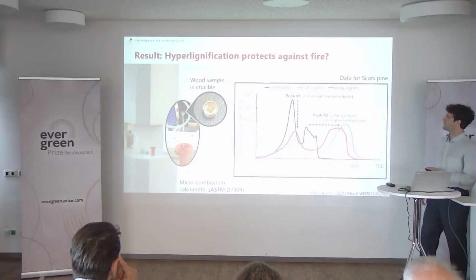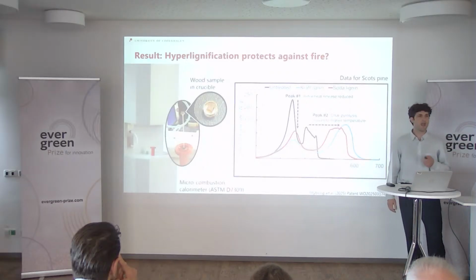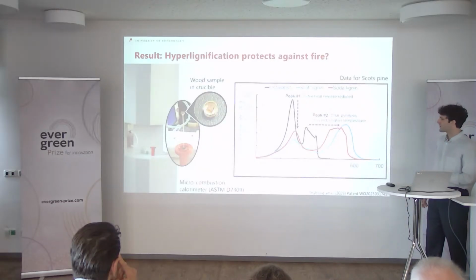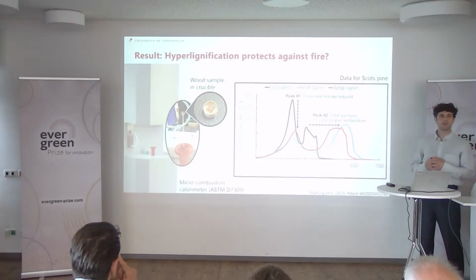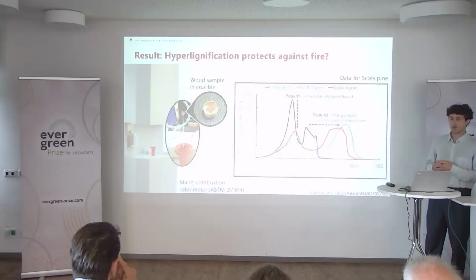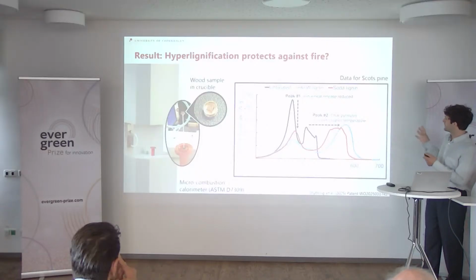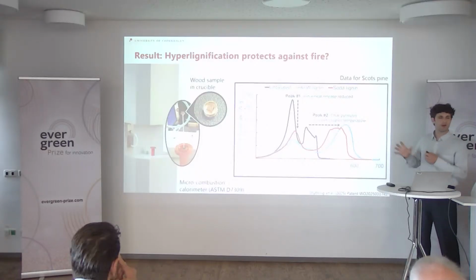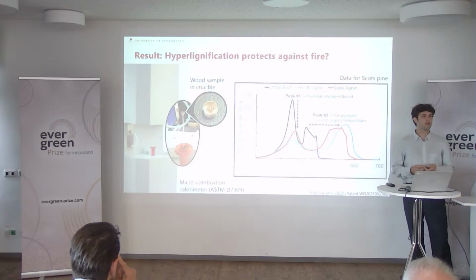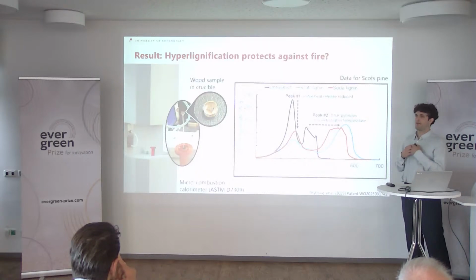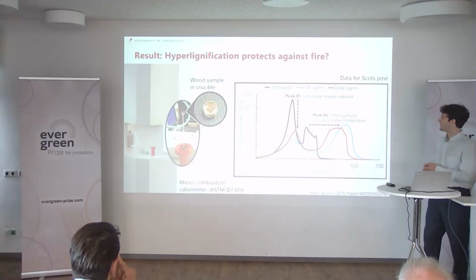And then we wanted to test fire retardancy, and we saw with microcombustion calorimetry that the initial heat release was reduced when we burned hyperlignified wood, while the char pyrolysis peak moved to higher temperatures, meaning that not only did we improve the fungal decay resistance, but here we are seeing an improvement in the fire retardancy of the wood.